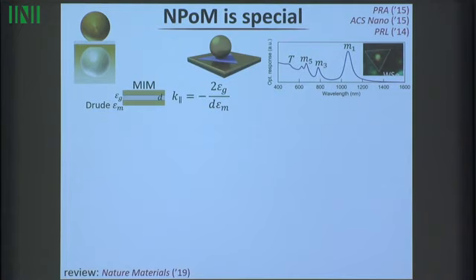And the way it works really is that I can think about underneath here, I have a metal, then dielectric, and a metal waveguide. Here the electrons can move, and this is a passive material in the middle. And it turns out I can calculate what light does in something like that. You would imagine that if I bring two metal surfaces together and they get much smaller than the wavelength of light, the light would be squeezed out. But it turns out electromagnetism is not like that. There's one extra mode of the system that doesn't do that, that really likes to be in the gap.